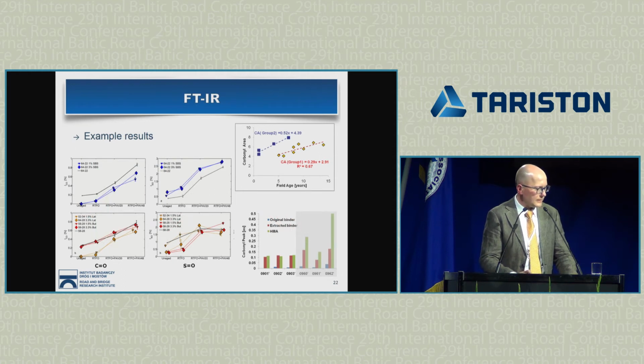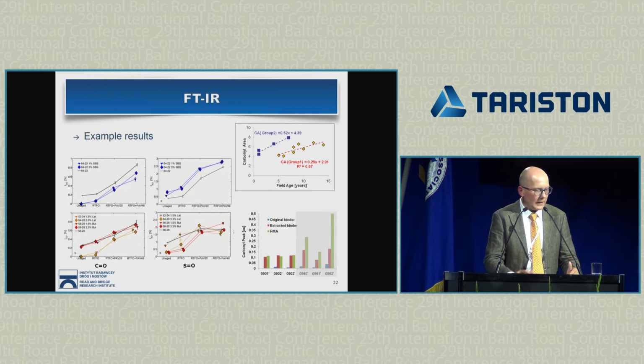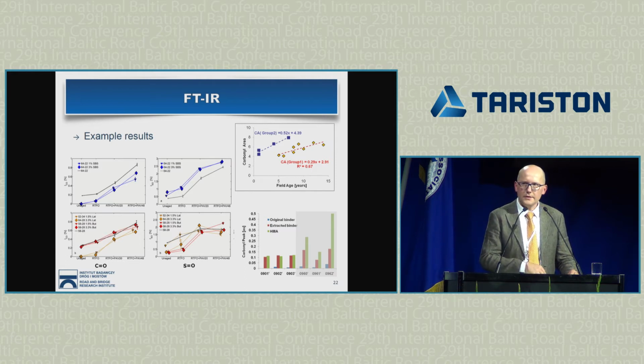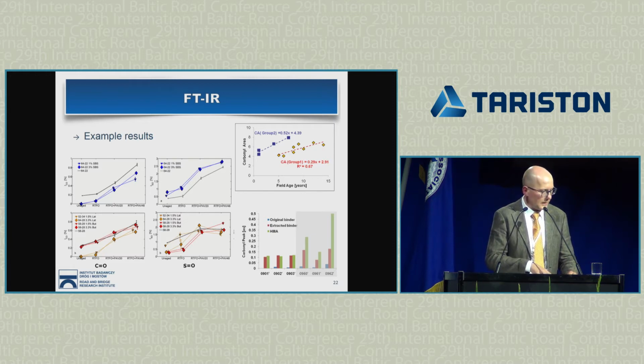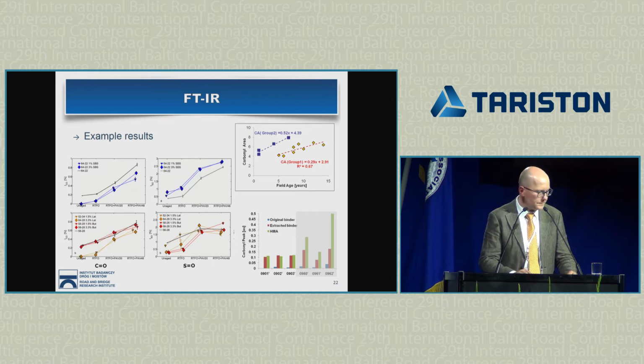So what you can see here are some examples. You can see the growth on the y-axis. In most of the figures, you can see the growth of the sulfoxide or the carboxylic acid, which are the products of asphalt oxidation, as we progress the aging here. On the x-axis, you will see either short-term aging or short-term aging plus long-term PAV or plus double PAV, for example. Yes, you will see this growth in each case.